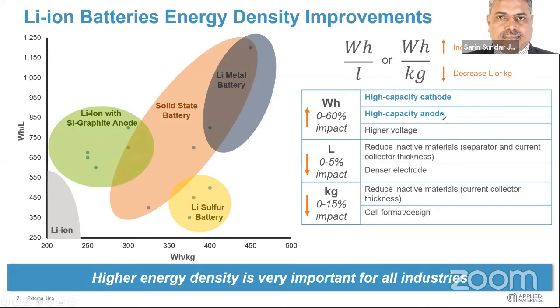If you look at what actually drives this, 60% of the impact you can get for the cost and energy density of the battery comes from increasing the watt-hour, either by high capacity cathodes or high capacity anodes. High capacity cathodes, everyone has been working on with various chemistries, NCA, LFP, the 4th generation of LFP now, and various other chemistries that people normally talk about. But predominantly, it has always been graphite for the last 30 years on the anode side.